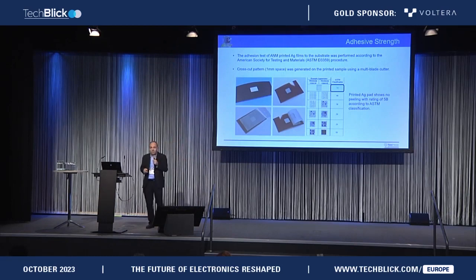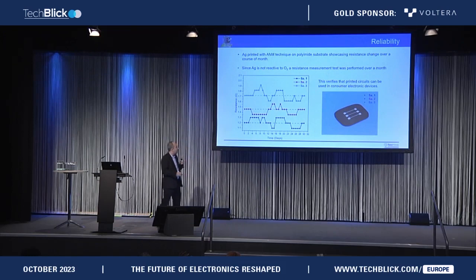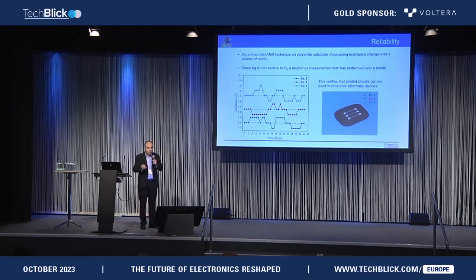Of course, adhesion is another very important parameter that we want to understand. We do the ASTM standard adhesion test on these, and you can see that we are getting 5B, which is the best adhesion you can get. We also do lifetime studies to see how it performs over time. This is up to a month. We have also done up to a year for silver, copper, and other materials.